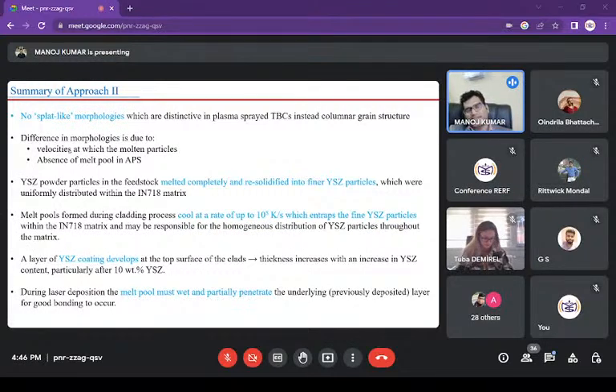Velocity of deposition is very different in this case, and there is an absence of melt pool in atmospheric plasma spray. In the plasma spray, melting is partial melting. It's not a complete melting, but in laser processing, we melt it completely. So when a complete melt pool solidifies, it has a different solidification behavior compared to solidification of a partially melted melt pool, if we call it melt pool.